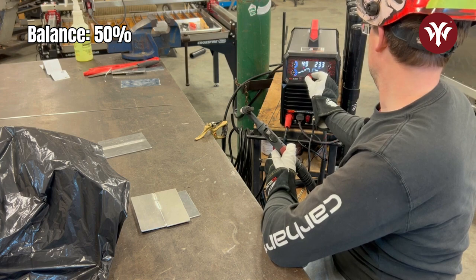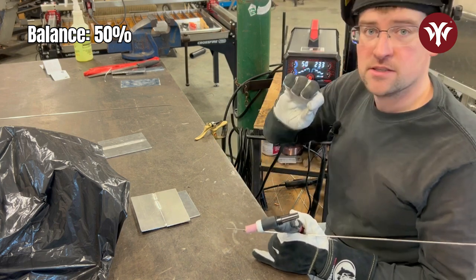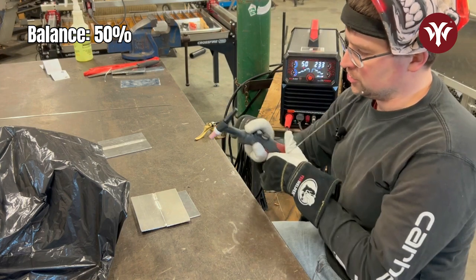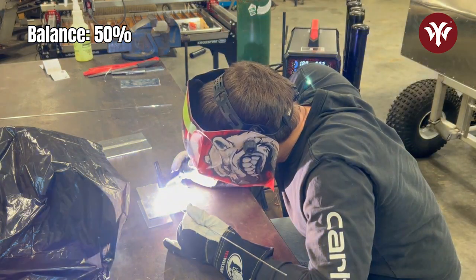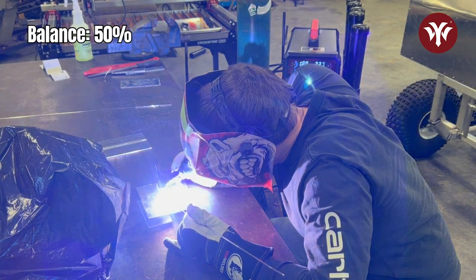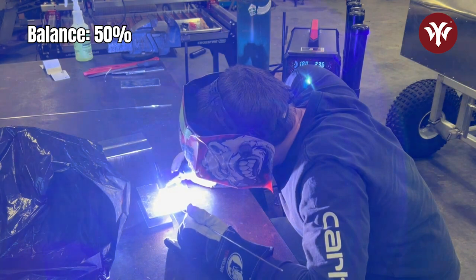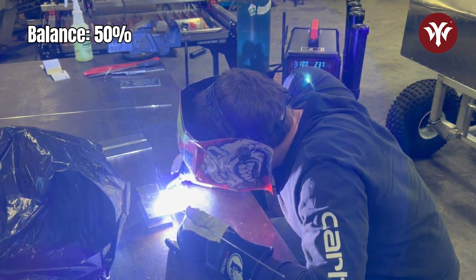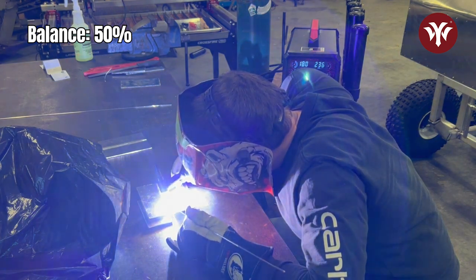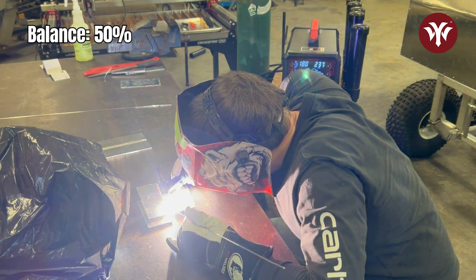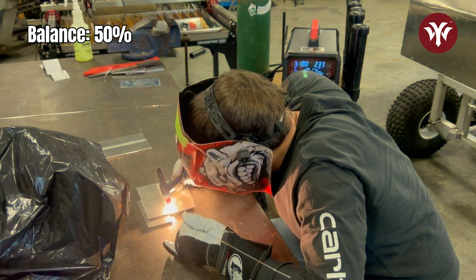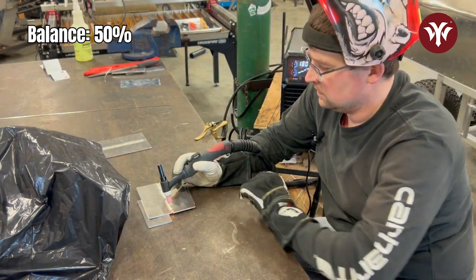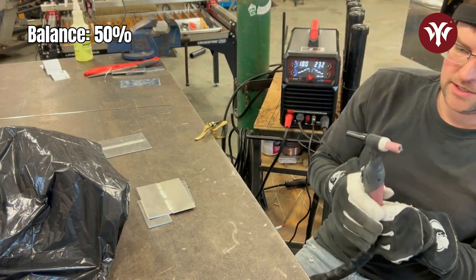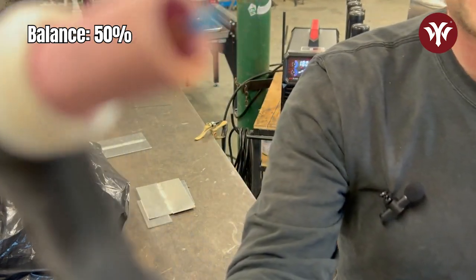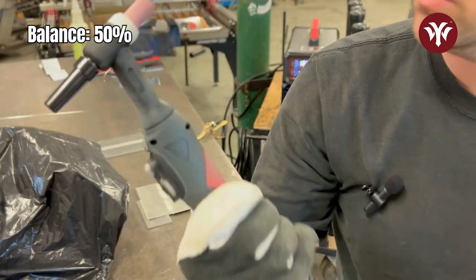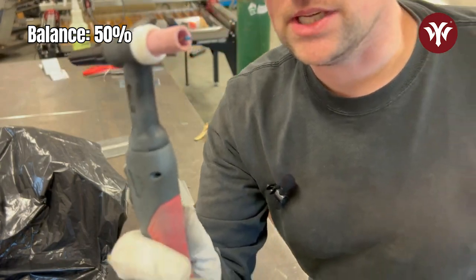Let's go to 50%, which for a material like this is really, really high, but I want to show you. Oh, I can hear the difference. Oh yeah, I'm needing much more current. The tungsten is balling up more than it ever has, because again, I'm putting way more heat into the tungsten. So it's probably a hard thing to show here, but that tungsten got a lot hotter. It actually balled up really nicely, but I probably would need more post-gas flow.